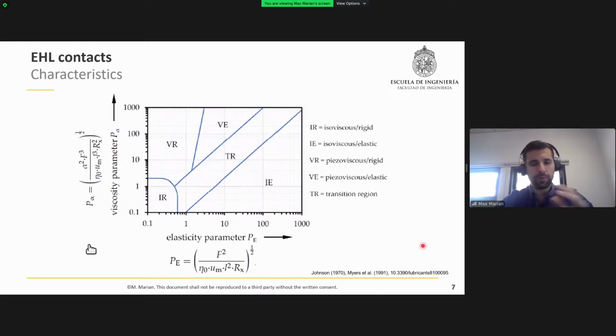Depending on the operating conditions and the involved materials and the lubricant, different effects can dominate the contact behavior, especially elastic effects and/or the piezoviscosity of the lubricant, which is the increase in viscosity under pressure. And using these kinds of dimensionless parameters that were suggested by Johnson, we can differentiate between an isoviscous rigid, an isoviscous elastic, piezoviscous rigid, and a piezoviscous elastic regime, as well as transition regimes in between.